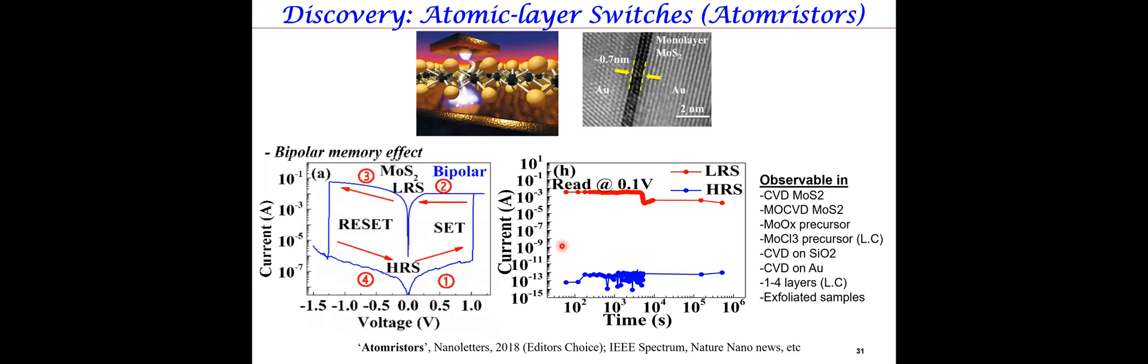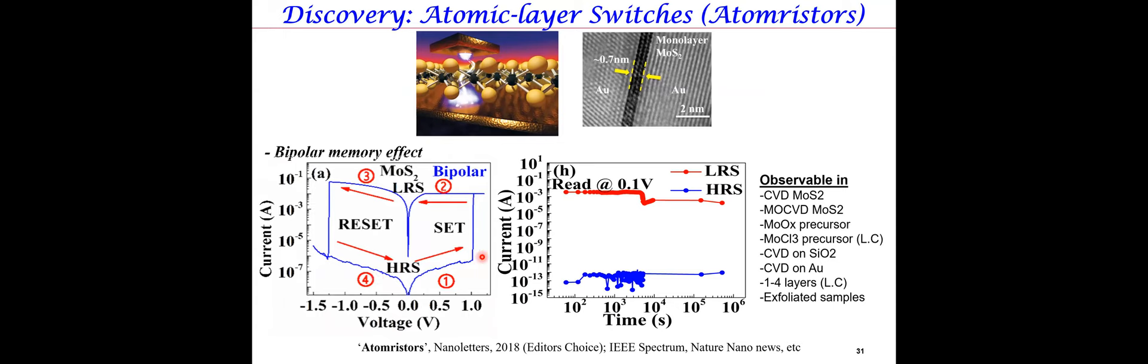When we started working on this, a lot of people believe that it was not possible to use 2D materials to make memristors. We showed after six months of our initial work the first memristors. We call them atomristors, which is memristors in atomically thin film. This is a standard bipolar memory effect. You see there's very low currents at the bottom of this graph. That's the high resistance state. Then we apply very high electric field around one volt, and then it goes to very high currents. That's a low resistance state. We can reset it back when we apply negative voltage. Very repeatable process.